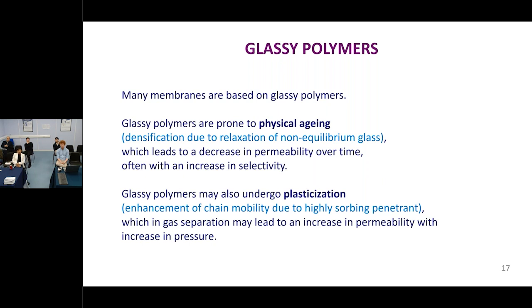But the thing about a glass is that it's not an equilibrium structure. The process of forming a glass is dominated by kinetics, by dynamics. And so we've sort of locked what is really a liquid structure into a sort of solid-like state. And what we're trying to do here is to use the bits of space that are left actually in our membrane process.